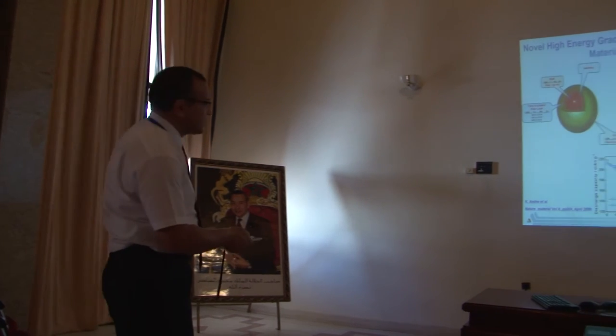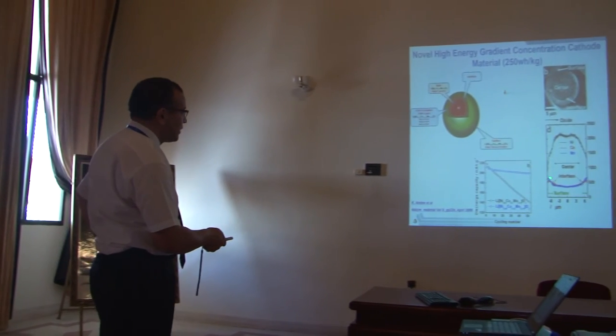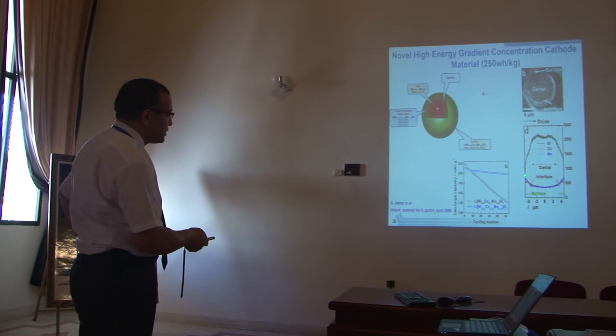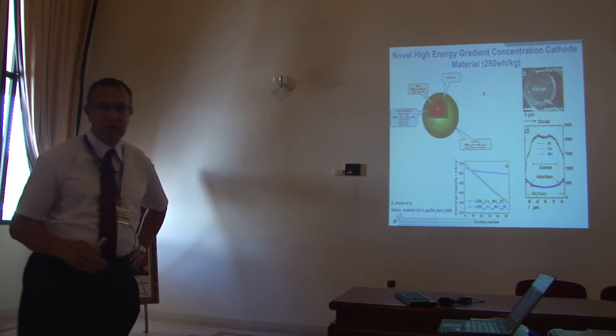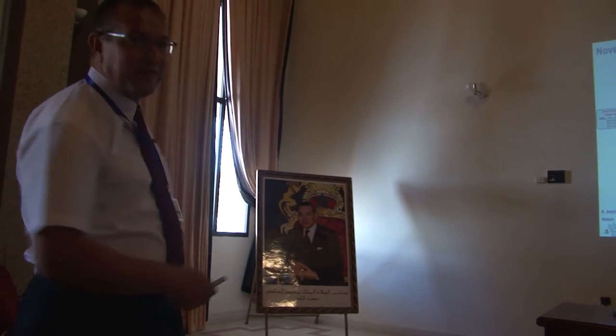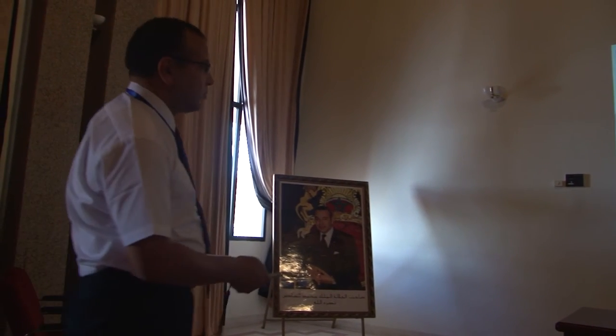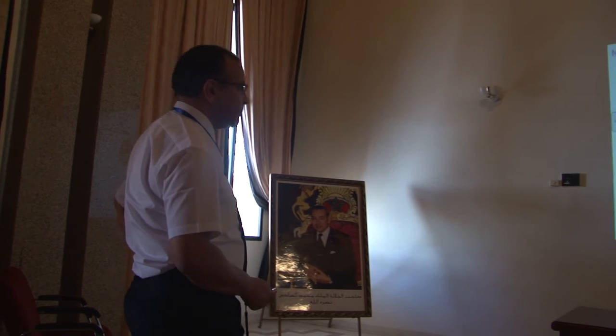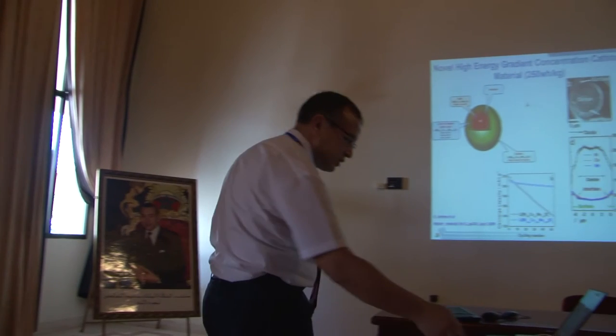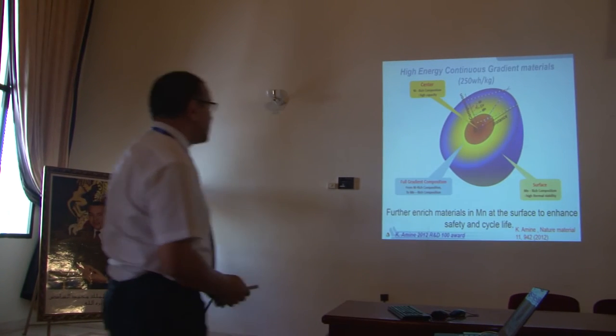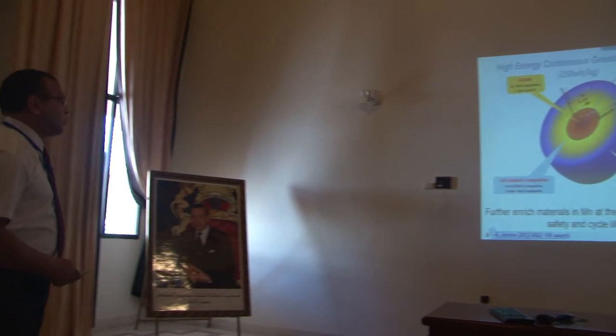The problem is, as you can see here, the shell is very small. So the concentration of manganese is very small at the surface. So we're talking about 15 years calendar life. Here I'm showing only 50 cycles. So clearly, we need to increase the manganese ratio at the interface, at the outer layer of the material. To do that, we change the concept, and we talk about what we call a full gradient material.